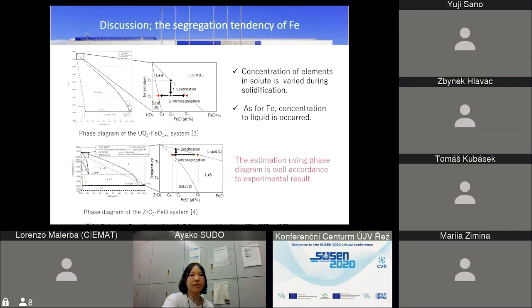Next is a discussion about the segregation tendency of iron using phase diagrams. This is a phase diagram of the UO2-FeO system, at high temperature. When liquid is solidified as temperature falls, the solute elements are distributed to solid and liquid. The concentration of FeO in the solid is CS, with lower FeO content, and the concentration of FeO in the liquid is CL, with higher FeO content.